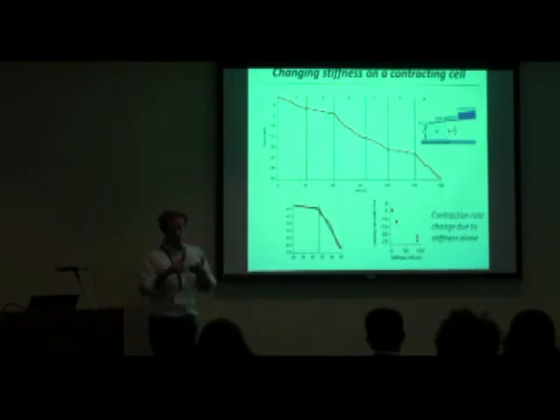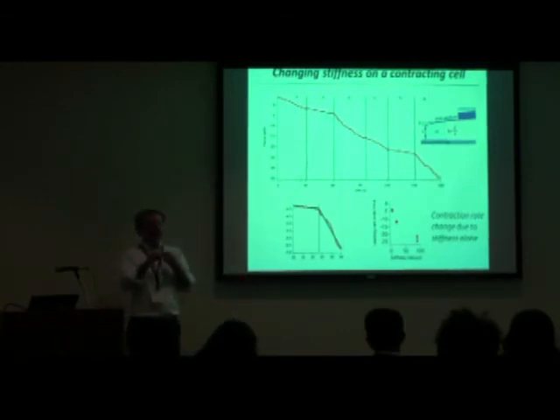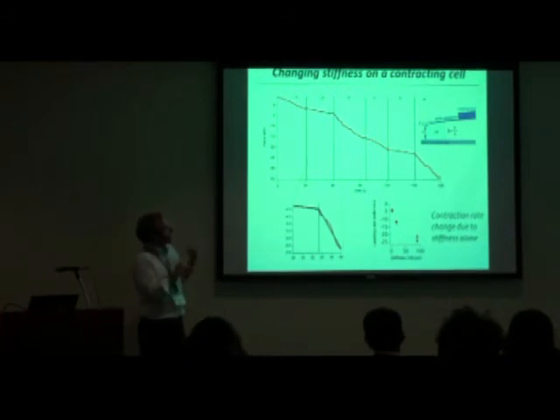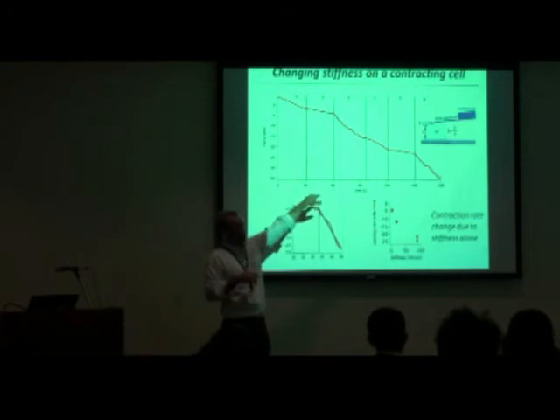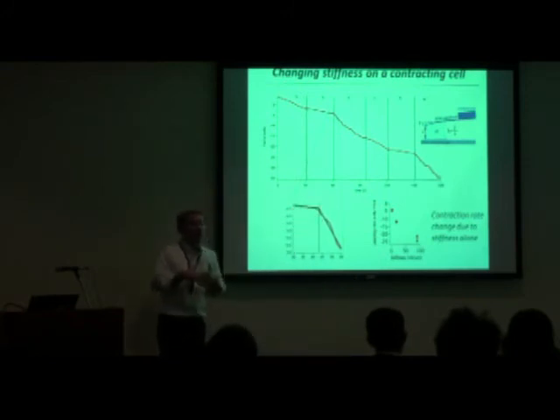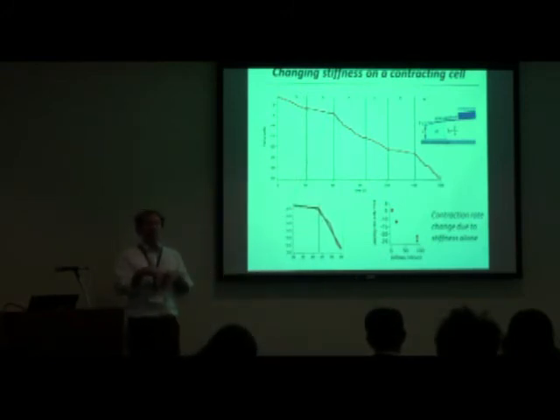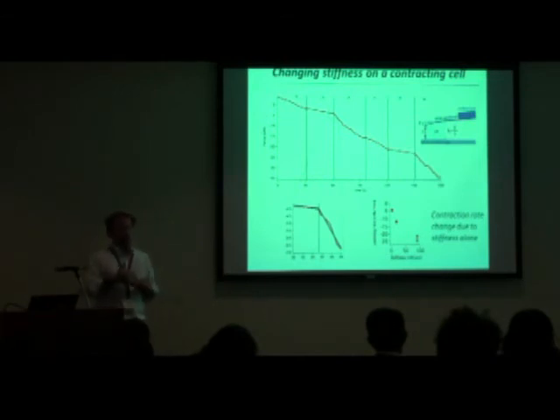I think these experiments show two things. One is that changing the stiffness in one of those directions is sufficient to elicit a response. So it doesn't just listen to the highest stiffness direction. It actually is watching for how stiffness is changing in multiple directions. Second, I think we can address your question by changing the substrate, making that a gel rather than a solid substrate, and asking if there's a third stiffness, how does this behavior change? We haven't tried that experiment, but that's a good idea.